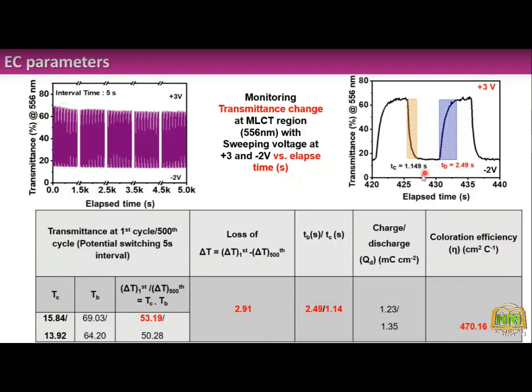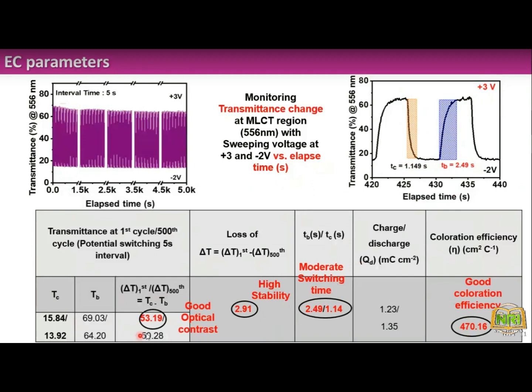And we can see the switching time. I told you from this time to this time. This is the bleach state, this is the color state. So this is called the coloring time. How much time is needed to change this color? This is only 1.149 seconds. Again, when it is going back to the bleach state, it takes only 2.49. So from these parameters we can see the optical contrast is very high, which is almost 53.19%. Again, high electrochromic stability up to 5,000 seconds, and more than that, I continued almost 10,000 seconds, but I have shown here only 5,000 seconds. Switching time is also very moderate. That means it will take very little time to change the particular color state, and coloration efficiency is also very good. So this material is highly applicable commercially.